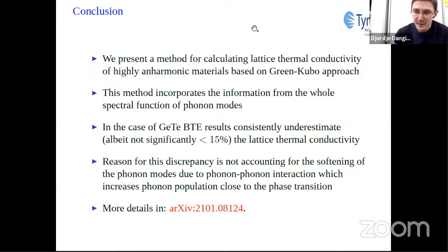Well, there are two good answers to that question. The first answer is that, in the modeling of the thermoelectric properties, the lattice thermal conductivity is somewhat decoupled from the electronic properties of the material. So you want to reduce lattice thermal conductivity without actually reducing the electronic properties of the material. Specifically in the case of germanium telluride, one would expect for very low doping that the lattice thermal conductivity will be the dominant factor in the total thermal conductivity. So that's the reason why we are not considering the electronic part of the thermal conductivity in this work.